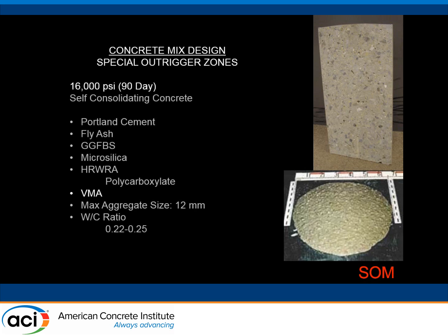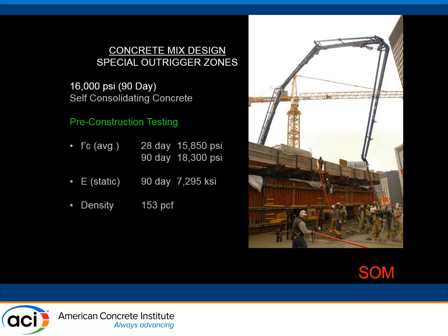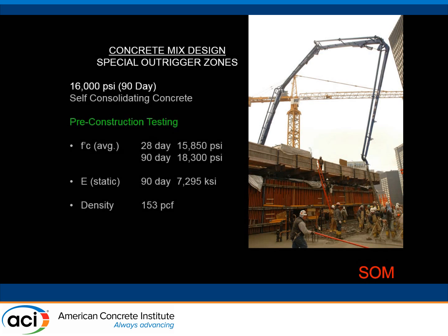So anytime we have self-consolidating concrete, you'll see that there's a common theme here where we're coupling the viscosity modifier with the water reducer. And the max aggregate size for these zones was 12 millimeters. Water cement ratio, pretty low, 0.22 to 0.25. We did some pre-construction testing of this mix because of the somewhat exotic nature of the mix. We saw that at 90 days we were up at about 18,000 psi, at least for the cylinders, and we got a static modulus at 90 days of about 7,300 ksi. The density came in at about 153 pounds per cubic foot.